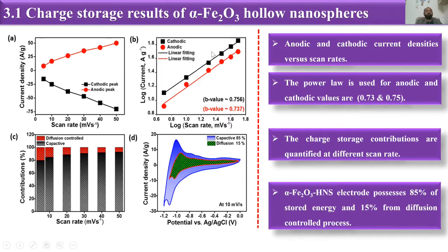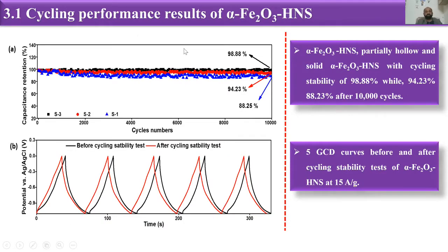Then we have done the cyclic stability for our materials, and we have got the stability of our alpha Fe2O3 hollow nanosphere, which was about 98.8% after 10,000 running cycles, and we have a regular pattern of our GCD curves for our system, which shows that these materials have good stability.